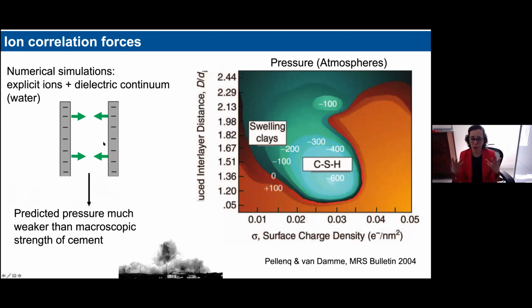If you look at these ion correlation forces, indeed you can have an indication that the material should be sticky. However, the cohesive strength that you get from this type of calculation is very weak, too weak to justify the use of cement in construction. Basically, they do not justify a building being able to hold its load.